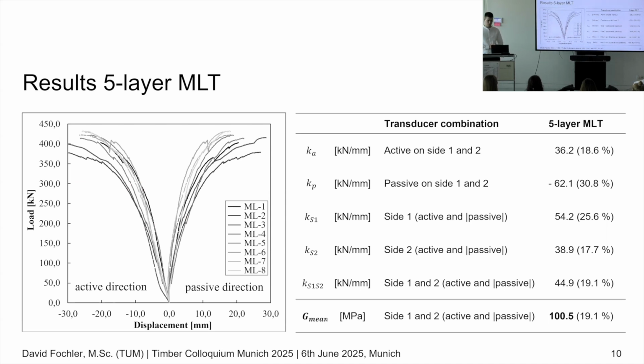And on top, the difference between each specimen was quite high. As we see here, the coefficient of variance goes up to 30%. So the mean value of the shear modulus is 100 megapascals. It's much lower than the CLT, and with a quite high variance.